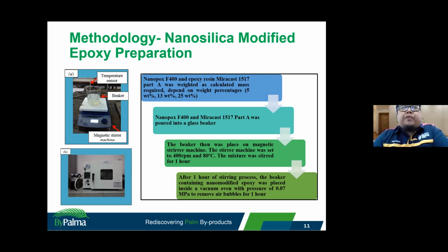As for the production of nanosilica modified epoxy, the Nanopox F400 and epoxy resin were weighed as calculated to get 5, 13, and 25 weight percent of nanosilica. Then the Nanopox F400 and Miracast 1517 were poured in glass beakers, and then we used a magnetic stirrer at 400 RPM and 80 degrees Celsius. Okay, the mixture then was stirred for around 1 hour.